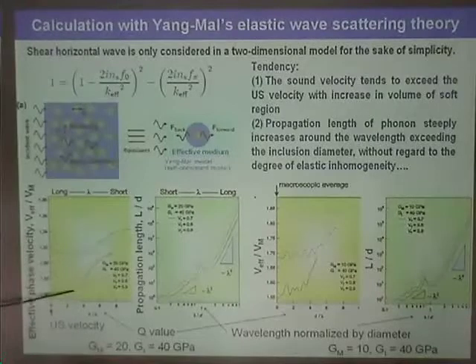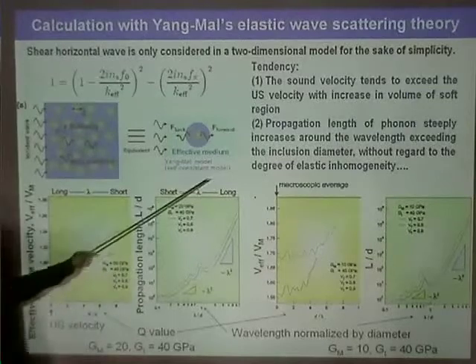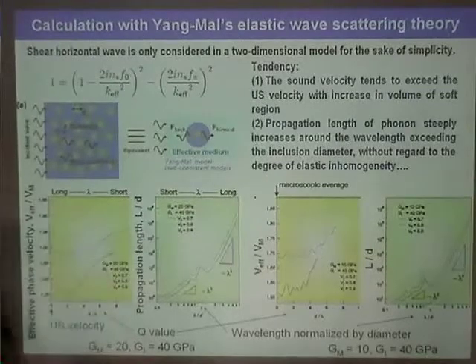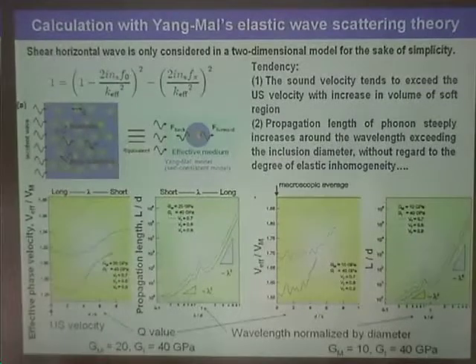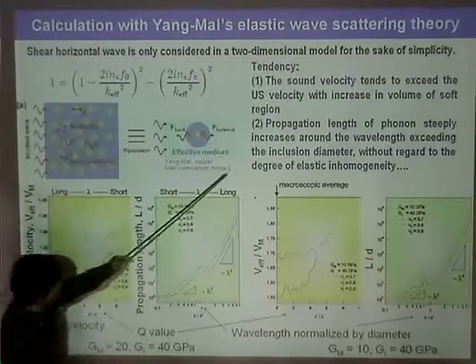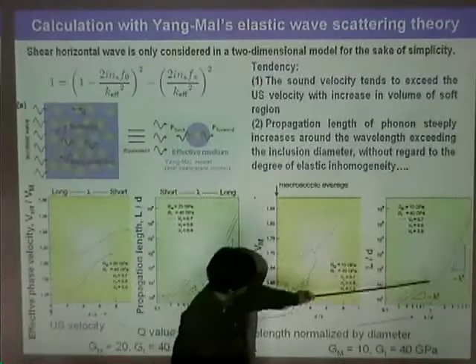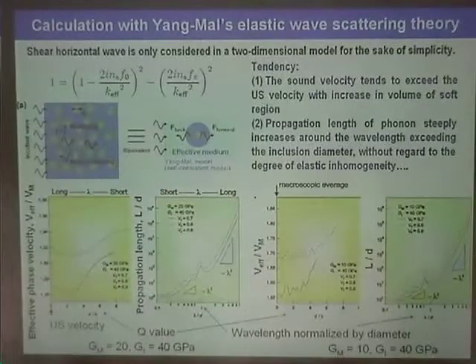Therefore, the increasing tendency is higher when the soft region fraction is high. The propagation length of phonons steeply increases around the wavelength exceeding the inclusion diameter, without regard to the degree of the elastic inhomogeneity. So in all cases we can see the same tendency.